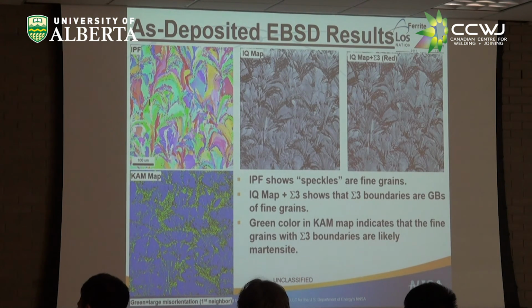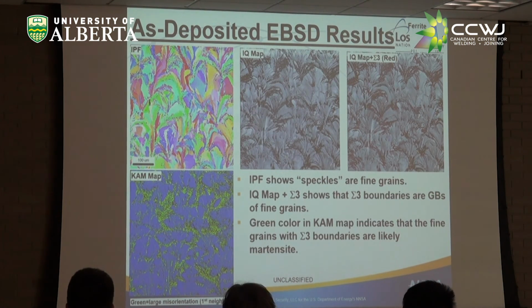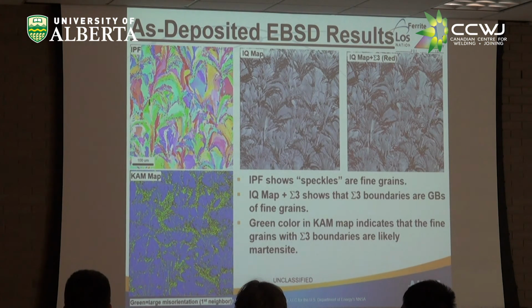If you can have it end up at the end of additive fully dense, where your thermal cycles and your spacing give you a fully dense deposit, and your heat input and perhaps preheating is sufficient to cause tempering of the prior beads exactly as you want it, then there can be advantage in doing that, because you would normally go through this direct temper as we spoke about earlier. But Lejeune is talking about the type 4 cracking that occurs in the, what is it again? ICHAZ, intercritical HAZ, which I think is where the martensite pockets come from in there. So I don't know the full answer to that.